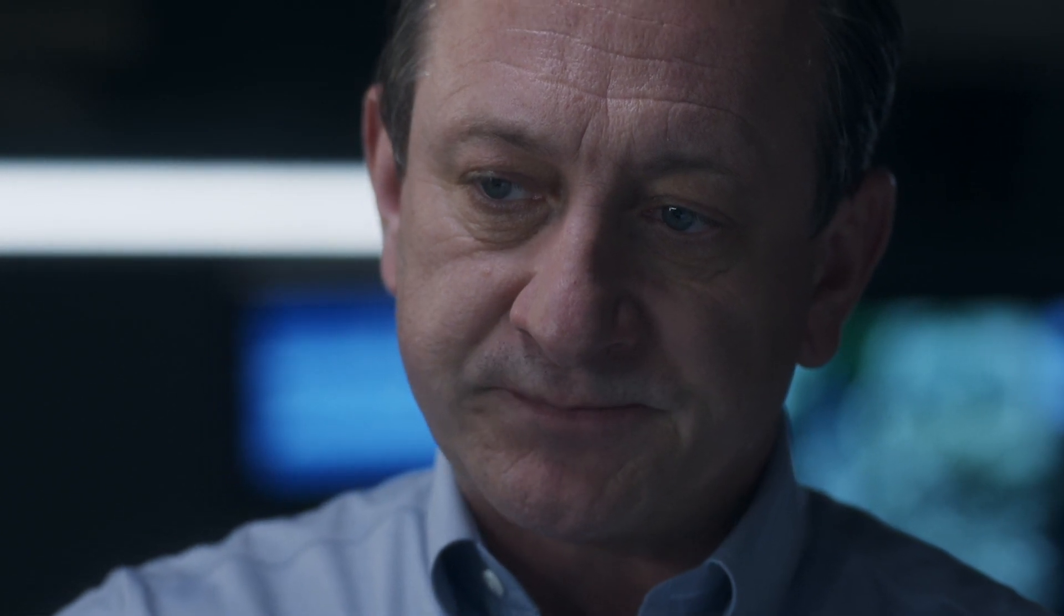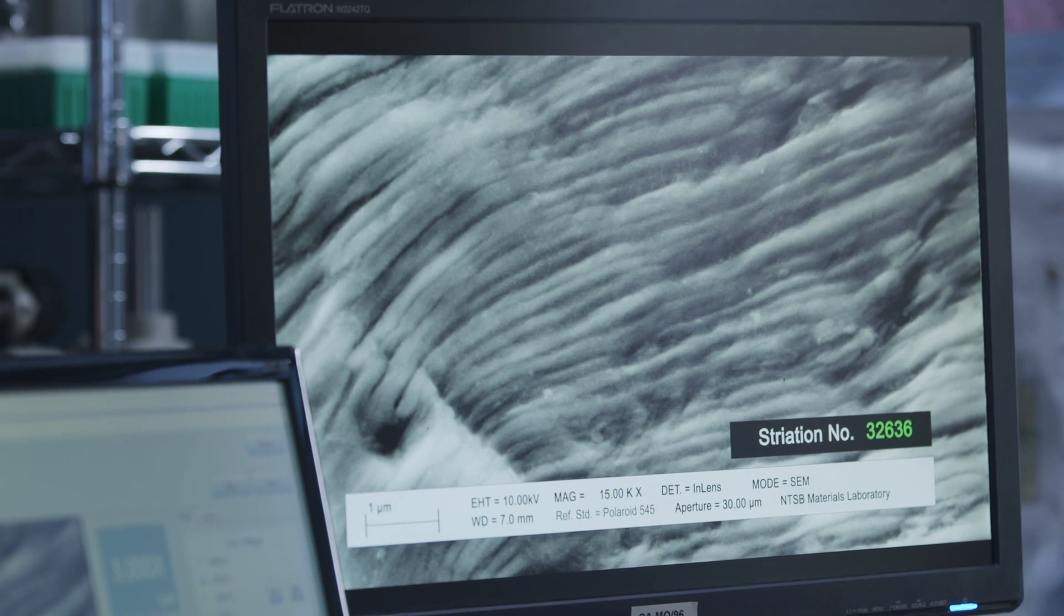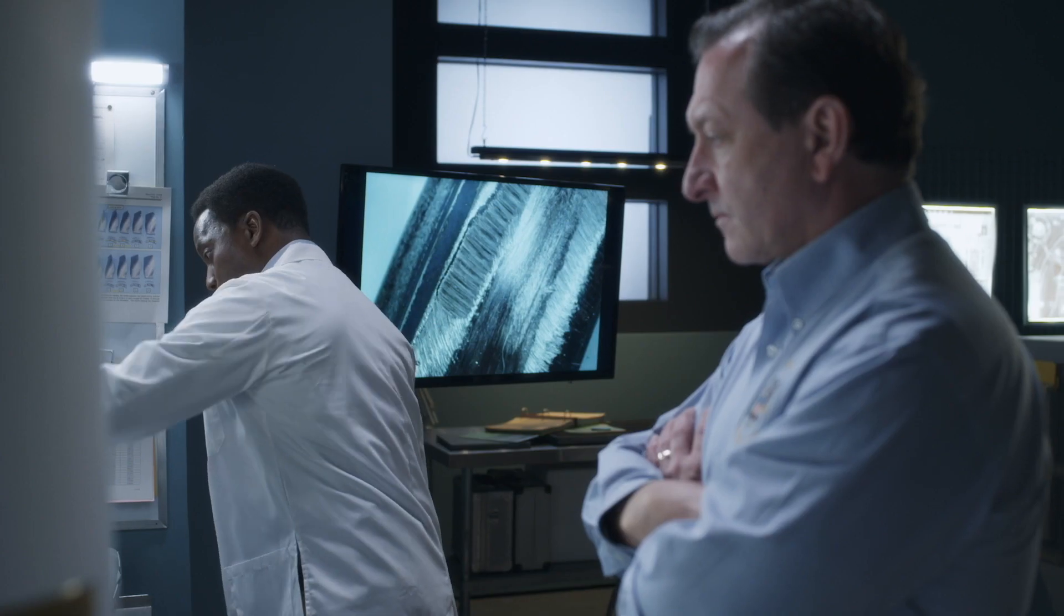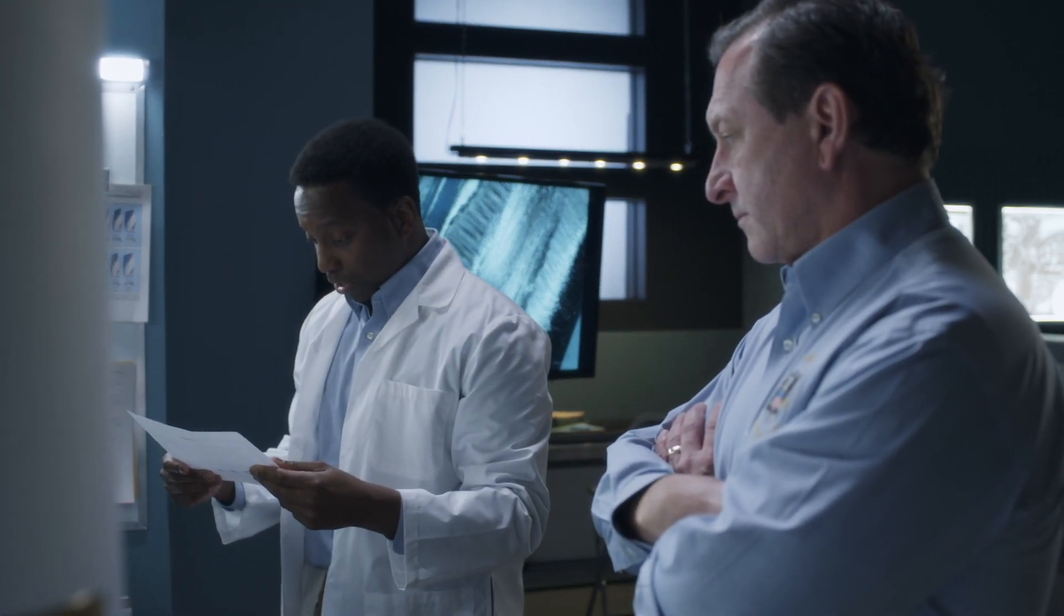What's that tell you? By counting the striations on the base of Fan Blade 13, investigators are able to date the beginnings of the crack. This crack could have started more than six years ago.